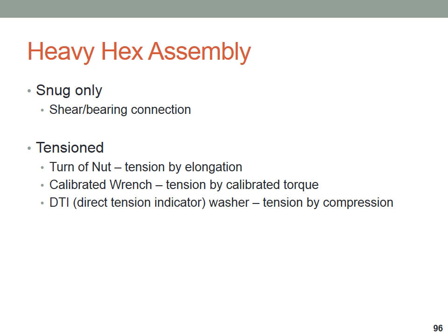Honestly, when we see the calibrated wrench method used, the calibration method is the iron worker, in many cases, just thinking the bolt is tight. We don't see a lot of companies that are actually doing the calibrated wrench method correctly. There are a handful. I'm familiar with a few erectors out there that do it very well and do it very regularly. But in a typical small project without a lot of oversight, a lot of bolts are just going into connections and ratcheted with an impact wrench until the iron worker thinks it's tight. That's his version of the calibrated wrench, and that practice is what gave that method a bad name for a while. But when it's used correctly, it can actually be used pretty well.